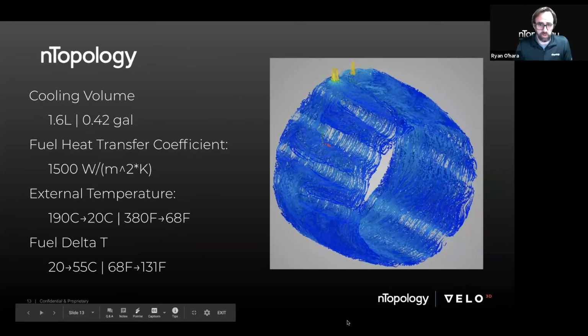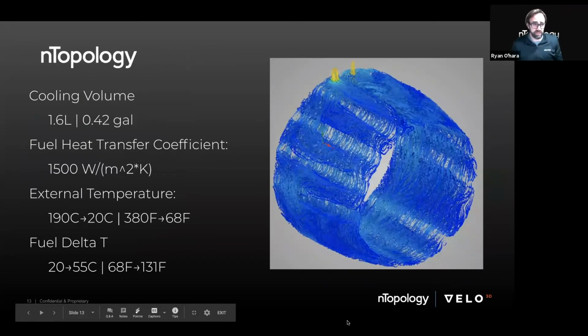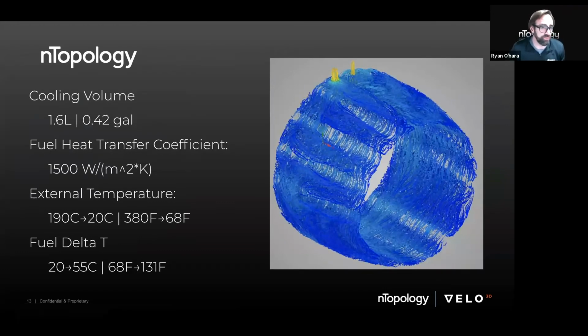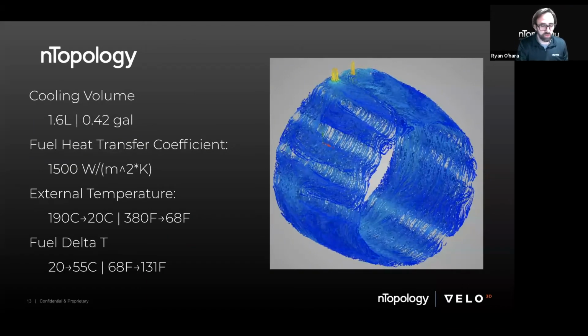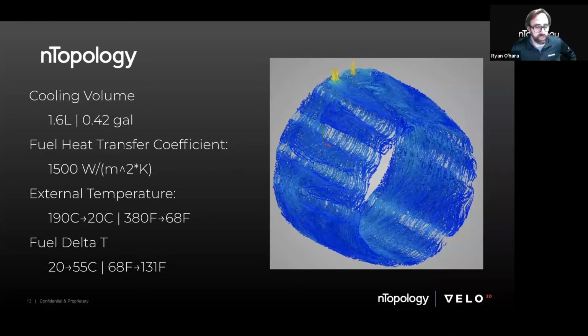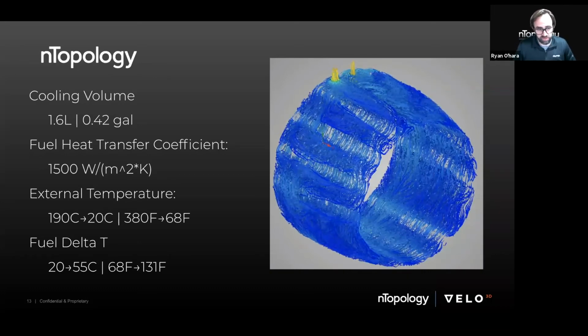So with that said, let's get to the goodies. The idea here is that we added almost 2 liters of fluid for cooling volume. In this case, it was going to be jet fuel. And then in our software, we took the geometry from the shelling operation, and working with one of my colleagues, we ran an ANSYS Fluent simulation. We'll talk about that. But we were able to calculate the fuel heat transfer coefficient so that I can do a simpler model in the design phase of this quite quickly. And I can do that all inside of our software.